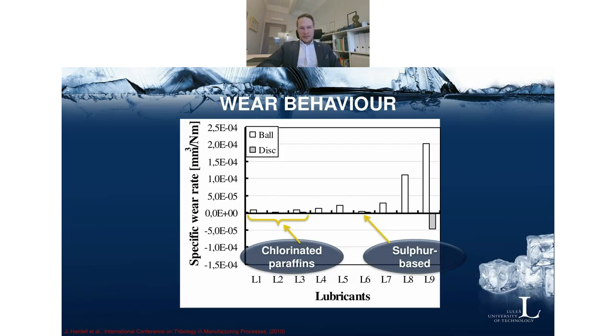So there is a good possibility to screen these lubricant chemistries when you design an experiment utilizing the real samples, real surface topographies that you are interested in studying. And we also correlated these values to real production tests in the rolling mills, and found a ranking which was very similar between actual performance in reality and tribotest performance.